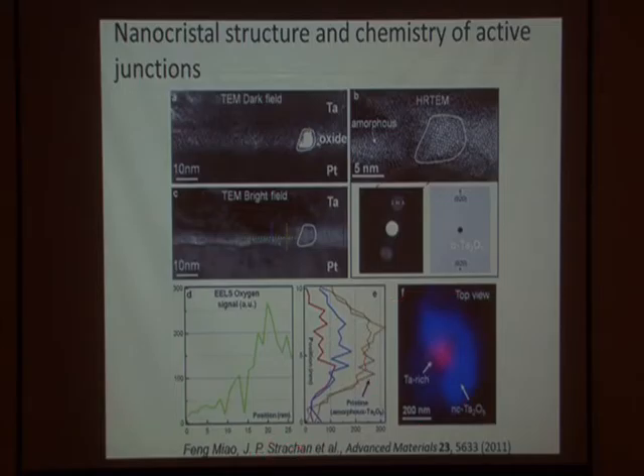This takes forever, and any temperature drift gets your sample out of the spot. We created spectroscopy maps, and with that we learned that the channel is actually composed of a tantalum-rich core and a tantalum pentoxide shell. So it's almost like a coax cable. The resolution is very poor, but this is as good as we can get it.